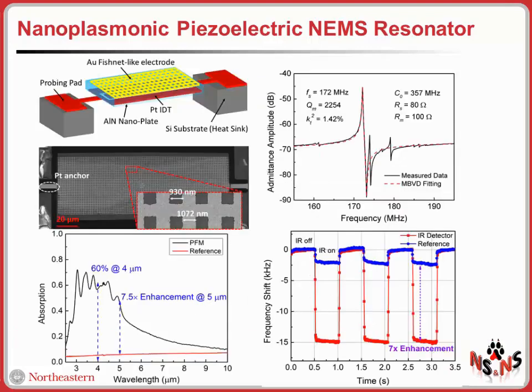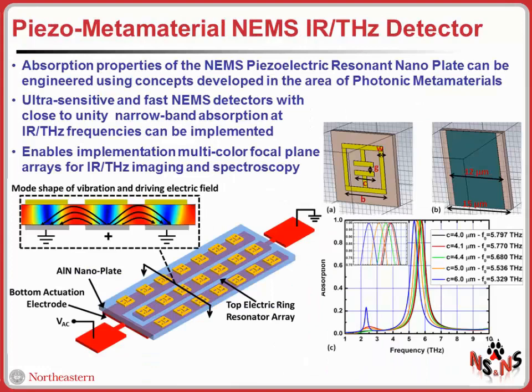What is also very interesting about this is that by changing the pattern of these plasmonic structures, for example, here you see a slightly different example, where we have a sort of complementary structure, we call it a fishnet metasurface, it's possible to completely change the absorption properties of this device. In this case, we have a broader absorption centered around 4 microns, for example. And still, the electromechanical performance of the device is not really affected by that. And these concepts can potentially be extended also to longer wavelengths.